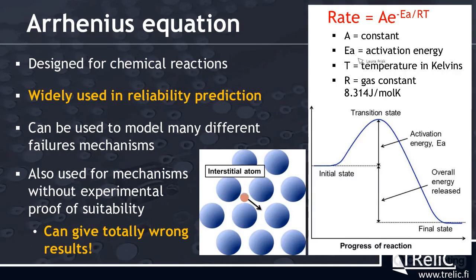So basically the equation describes how this happens. We need the activation energy to use this. And for example, for electronics, there are lots of lists where you can check what kind of activation energies have been found from studies for certain structures. But the problem may be that the activation energy is still not suitable, for example, for a new component which has different materials or a different structure. But this equation has been used for many different things. For example, here is diffusion, which quite often can be studied using the Arrhenius equation.